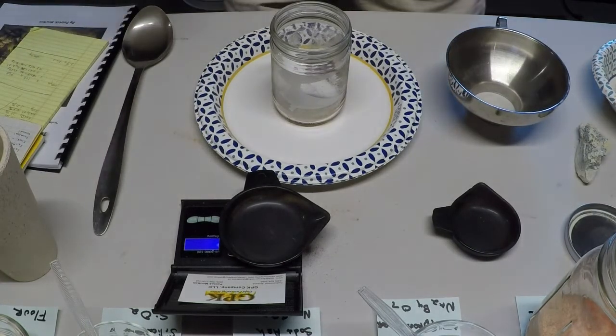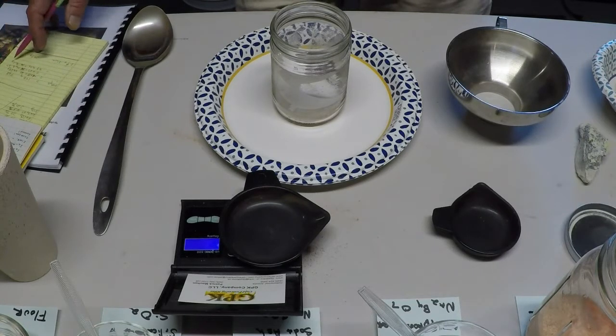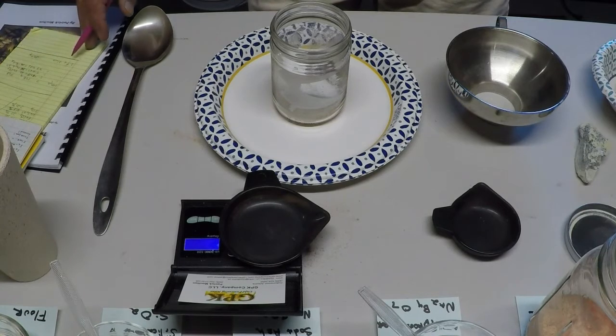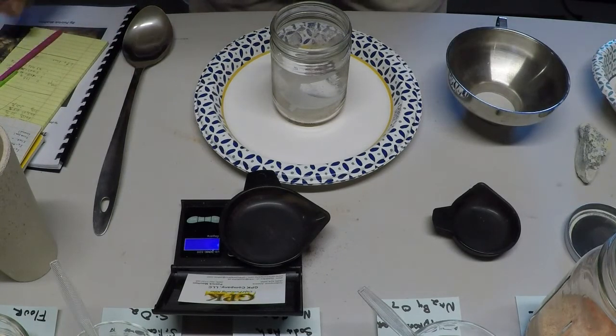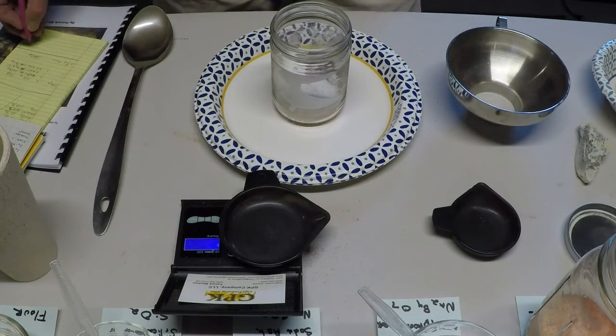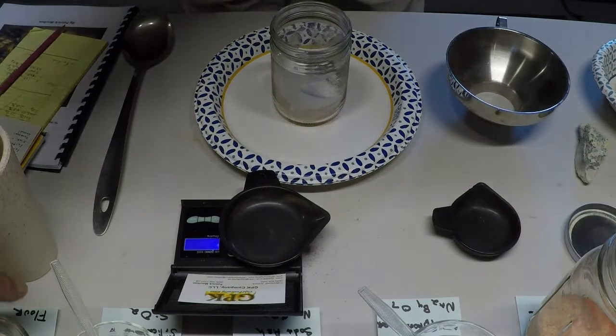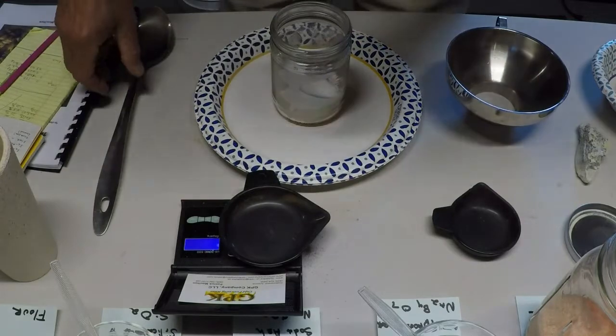So theoretically at this point I believe our oxidation is complete. I believe we drove all of the arsenic away, and so I'm going to add enough flour at the rate of 1 gram of flour will reduce 11 grams of lead oxide to metallic lead. So I'm going to add basically 2.7 grams of flour, which would give us 29.7 grams of lead oxide.